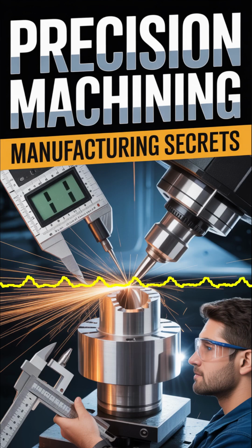And the genius is in tuning that recipe, right, by changing the amount of cobalt. That's the core trade-off. If you use low cobalt, maybe 3 to 6%, you get the absolute highest hardness and abrasion resistance. But it's brittle. So that's for finishing, for micro tools where impacts are low. And if you crank up the cobalt, if you go to high cobalt, say 10 to 30%, the material becomes much, much tougher. It has great impact strength. So that's for heavy roughing, interrupted cuts, even things like mining buttons that get hammered all day. So a machine shop must have drawers and drawers of different inserts just for subtle changes in a job. Oh, absolutely. The tool strategy is defined by these subtle changes.